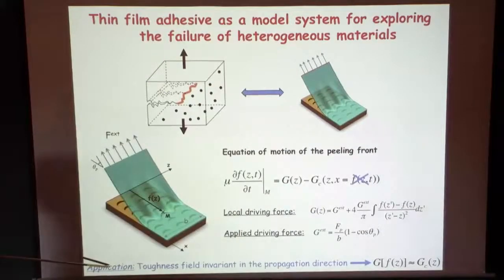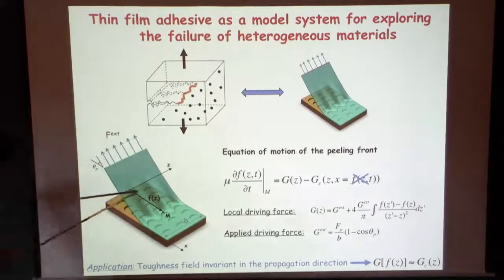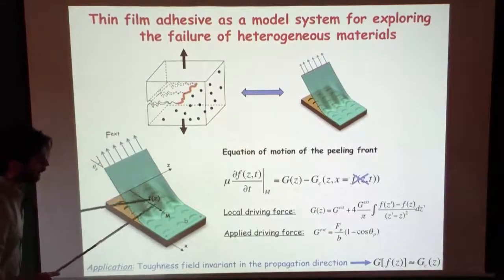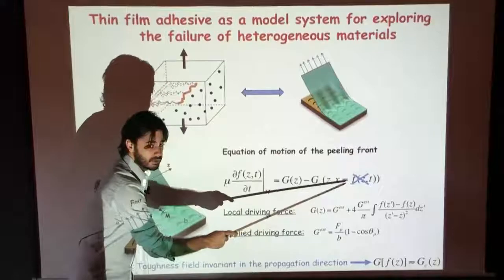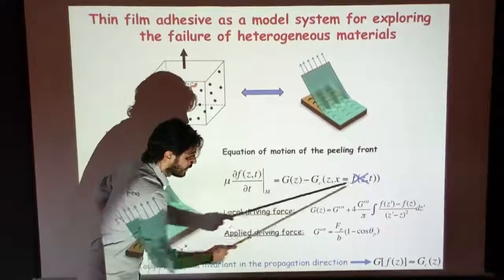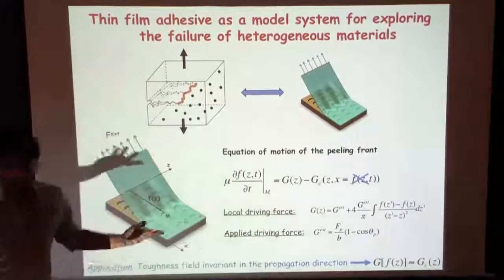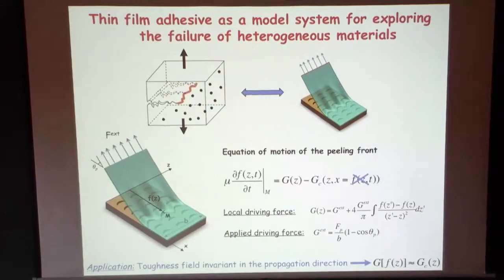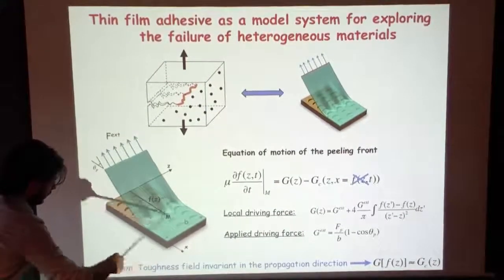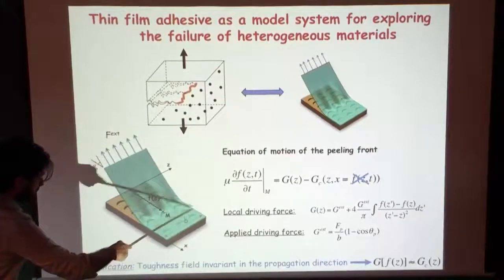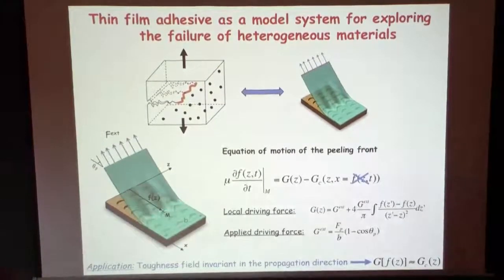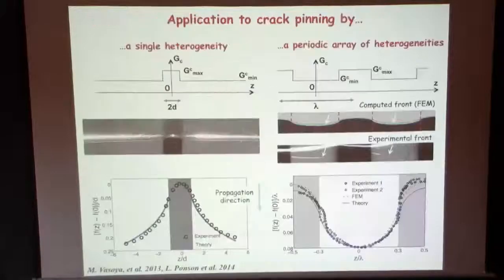So the first application, to compare the model with some experimental observation, is to consider a perturbation, a toughness field or fracture energy, invariant in the propagation direction. Then I get rid of all the complexity I talked about previously. I don't have the unknown geometry of the front inside the heterogeneous term, and I can solve the solution analytically. What do I have if I impose G_c independent of x and depending on z only? I have a stationary front shape that I can predict and compare with experiments.